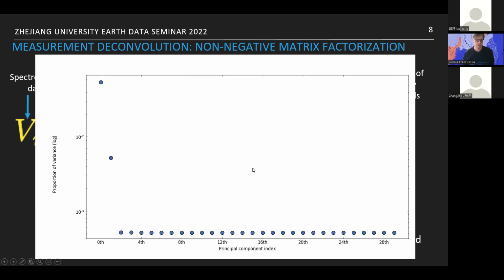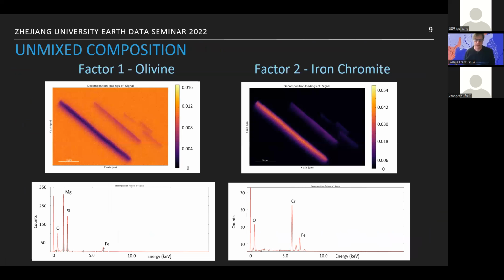And what we're able to do then is first examine that we can see that two factors are needed to explain about 87% of the data. And everything above this is uncorrelated noise. And this is very true because in the case of this map, it's a low count spectra. So we're trying to work very fast as well. And when we make that condition, we're able to get these two factors that look like both the chromite, the chromite here in factor 2, and the olivine in factor 1.